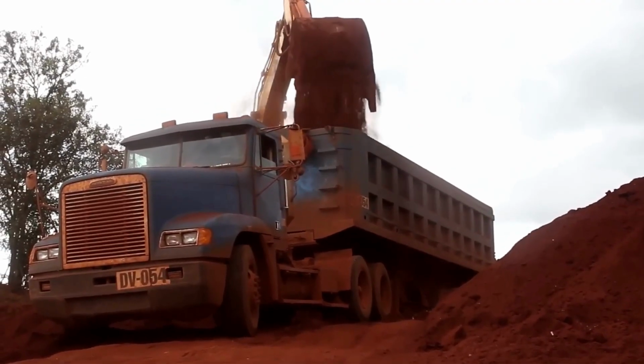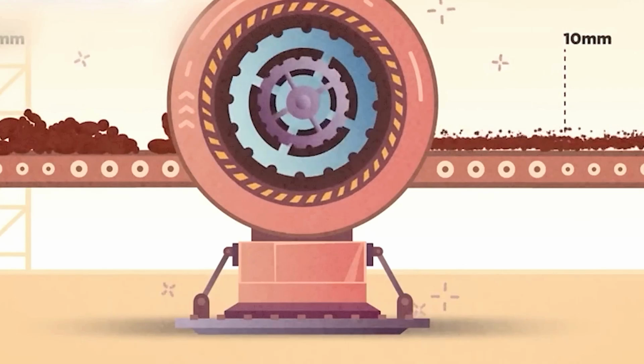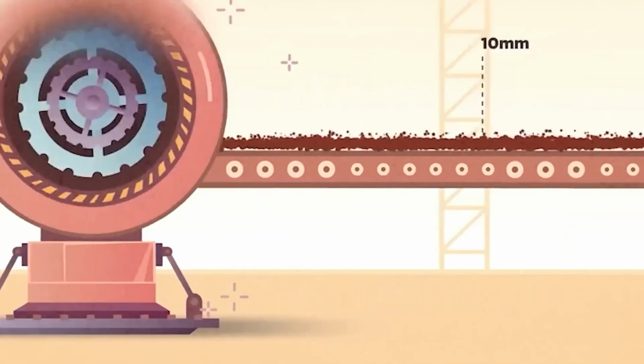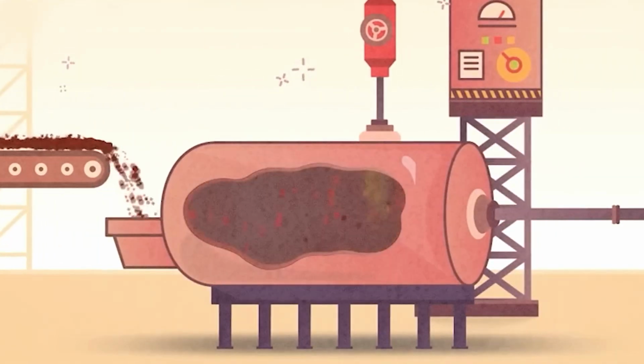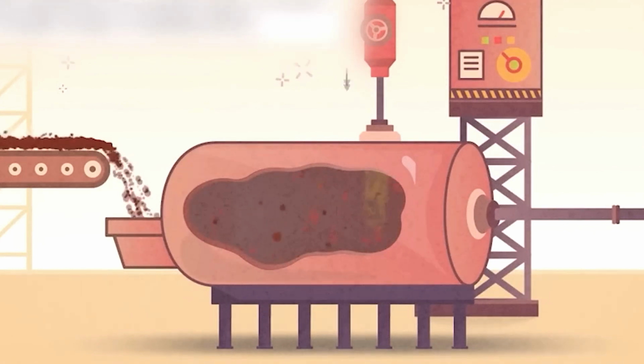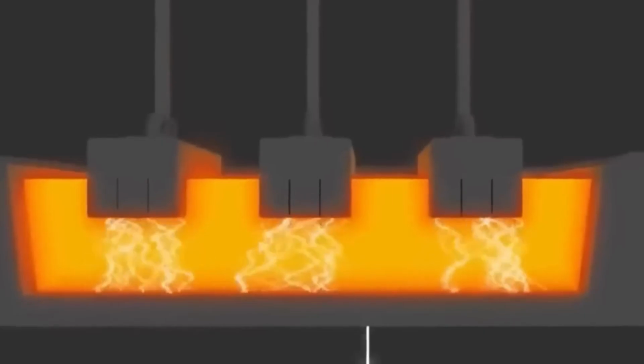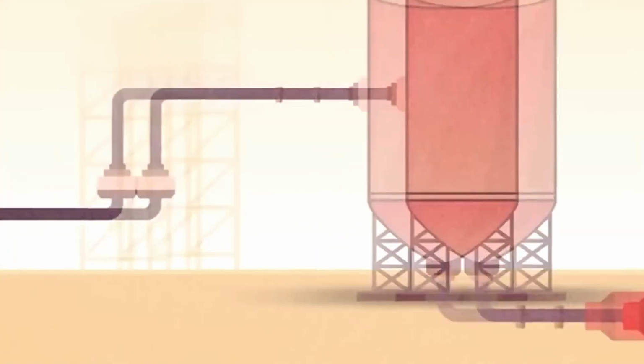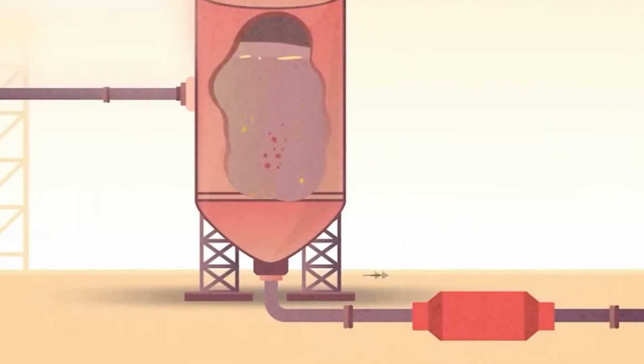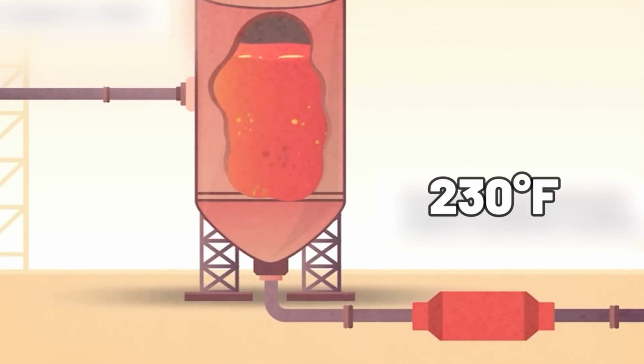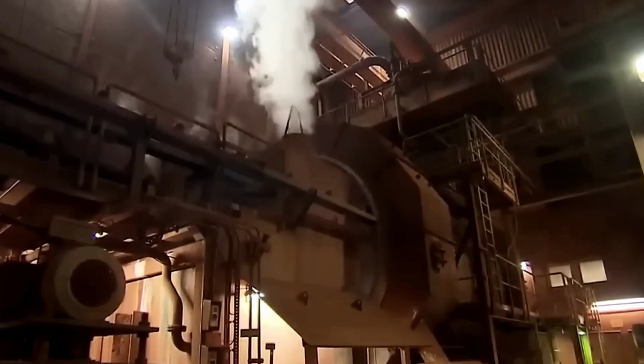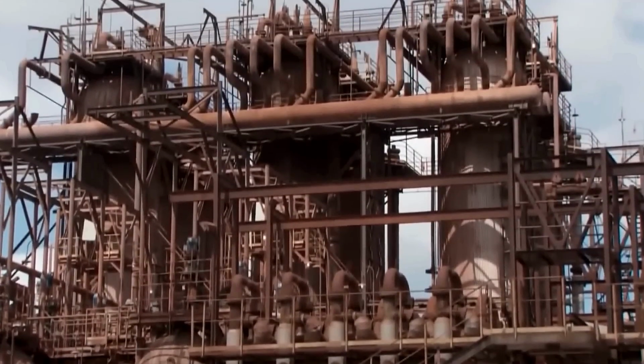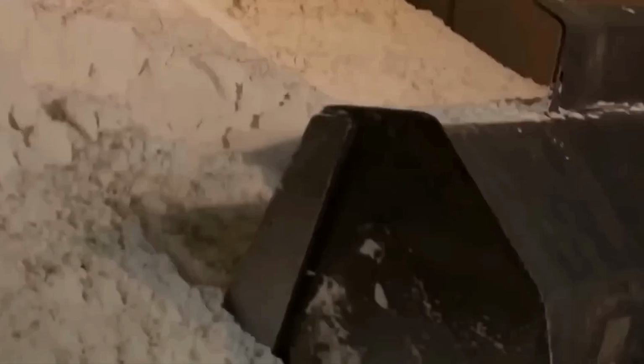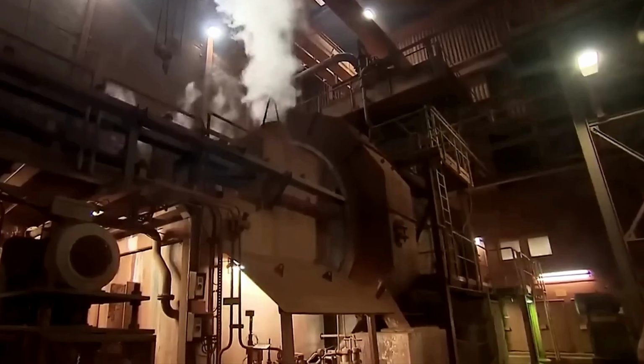Once extracted, the next step is refining. The process begins with the bauxite being mechanically crushed before being mixed with caustic soda and processed in a grinding mill, a watery suspension of finely ground ore particles. The slurry is then pumped into a digester, a high-pressure tank that functions like an industrial pressure cooker. Inside, it is heated to temperatures around 230 degrees Celsius. The mixture remains under these conditions for anywhere from 30 minutes to several hours, allowing the caustic soda to break down the ore efficiently. Additional caustic soda may be introduced to ensure the process is as effective as possible.